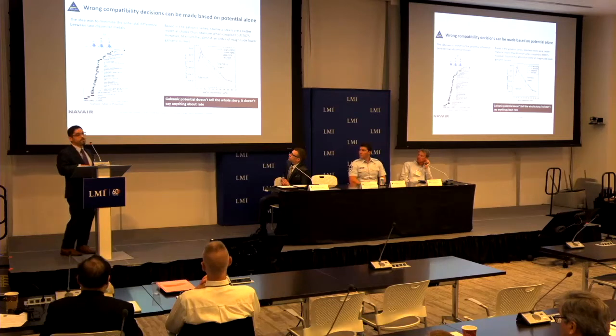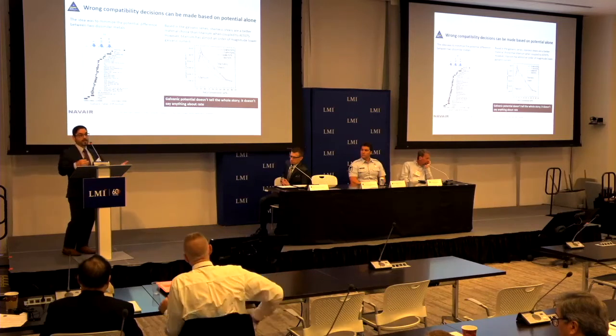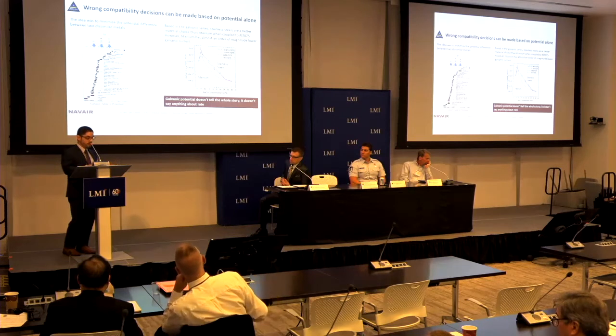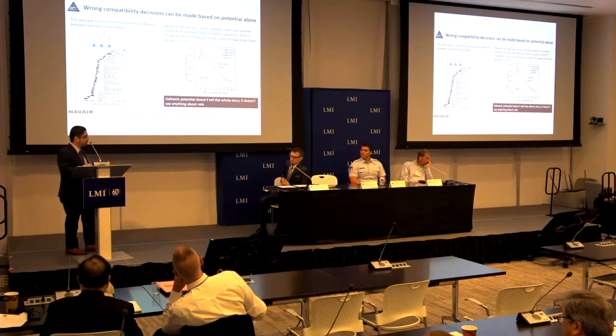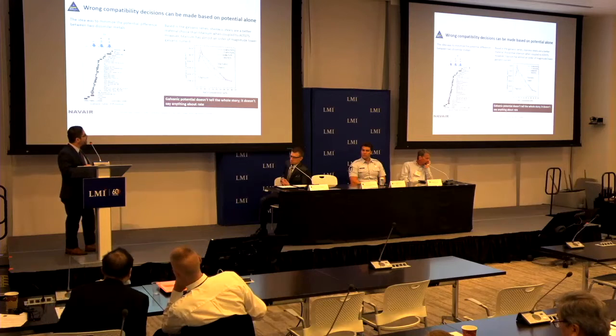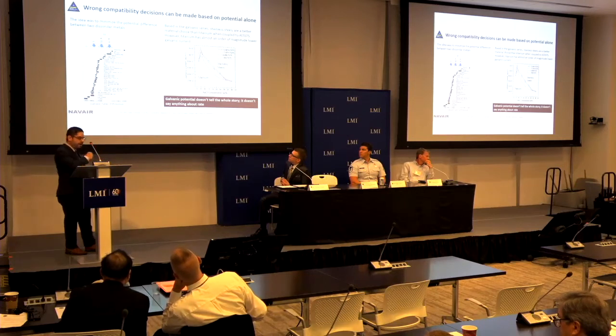But if you actually take the data, the rate data, the corrosion data, it tells you that titanium gives you an order of magnitude or more or less current between these two metals. So obviously, the old galvanic table based on potential was not giving us, on many occasions, the right decision making. And it is because galvanic potential doesn't tell you the whole story. And if you remember that little diagram, that little hump is how quickly things happen.